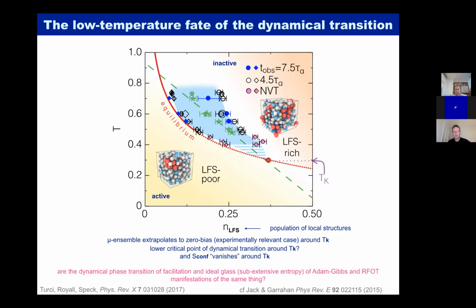So my equilibrium liquid is the red line. I drop the temperature, I get more local structures. So I'm plotting temperature as a function of the number of local structures. My active phase, my local structure poor phase, is on the left-hand side. My local structure rich phase is on the right-hand side. I have this dynamical phase coexistence between these two, and this has a lower critical point. And it turns out this lower critical point occurs close to the Kauzmann temperature.